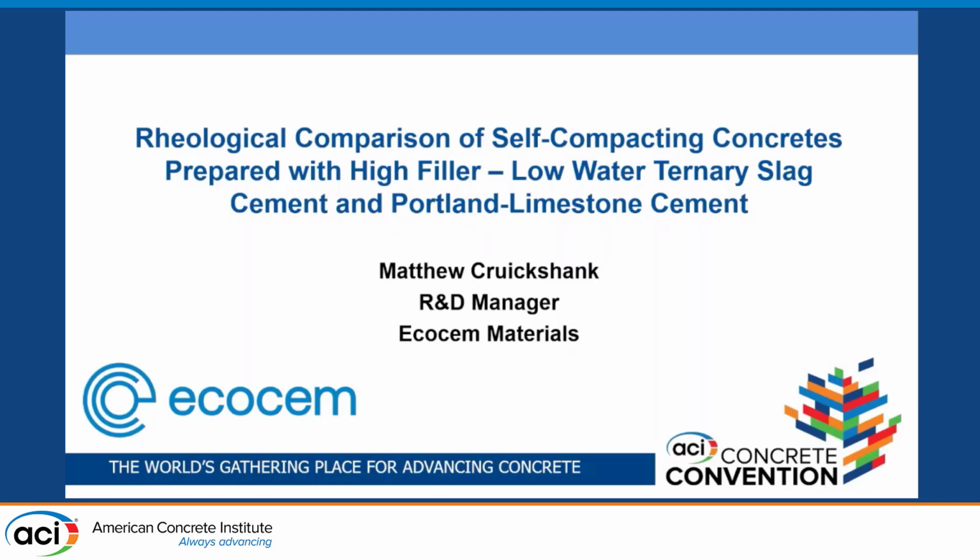We saw today an example of 70+% of slag, only 10% clinker. So when you see these very high numbers of cementitious materials, rest assured that very little of that is actual Portland cement. And I think this is obvious in this presentation. And Matthew will be presenting some work for Ecocem materials, where they have been working diligently for many years on the design of binders that are not the blended of different SCMs and Portland cement, but a binder that contains very low clinker factor.